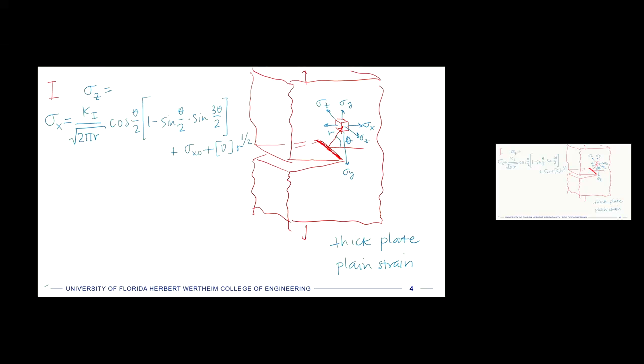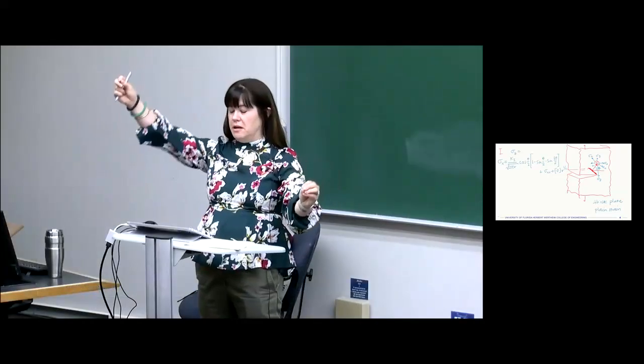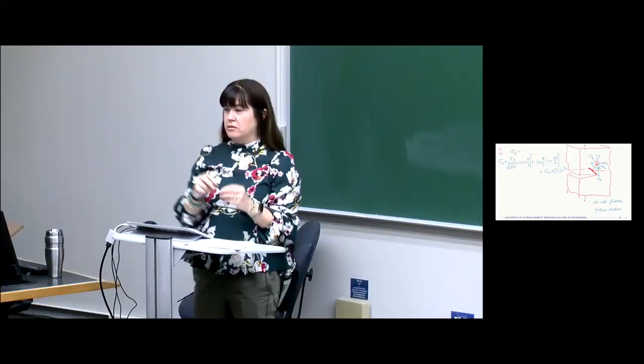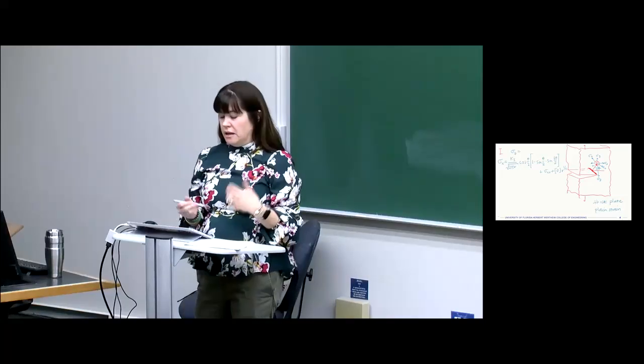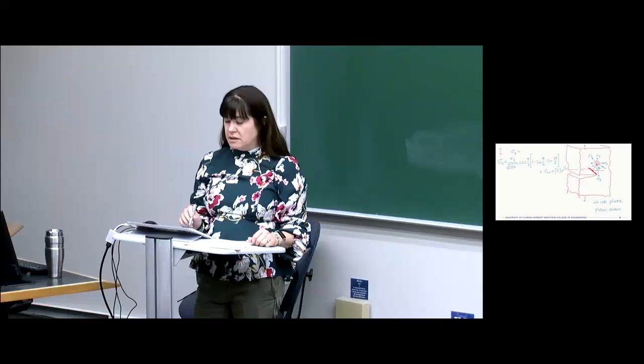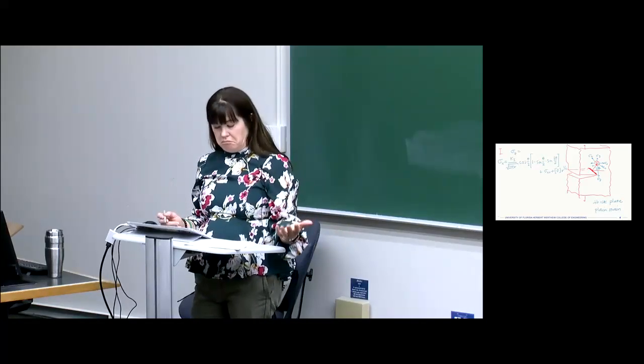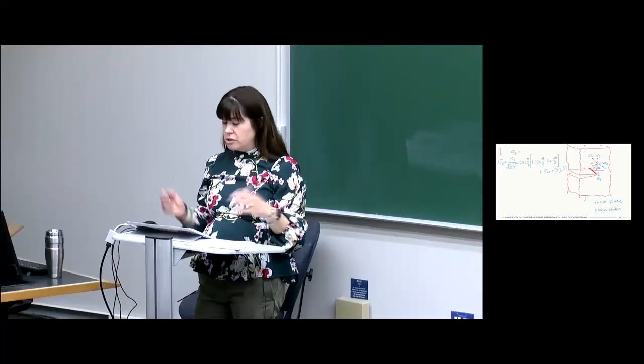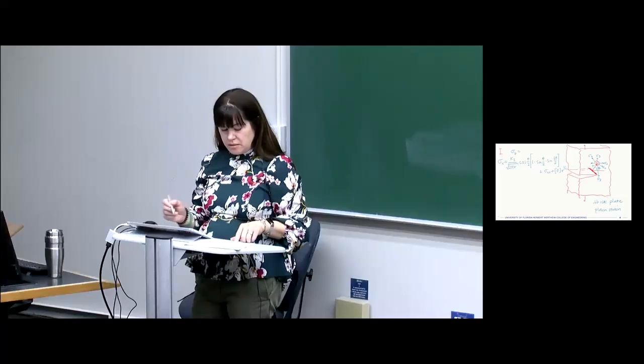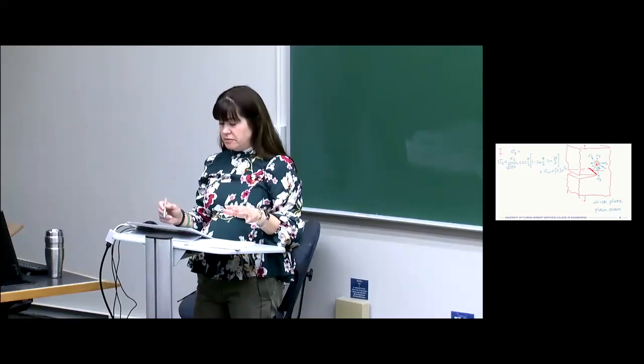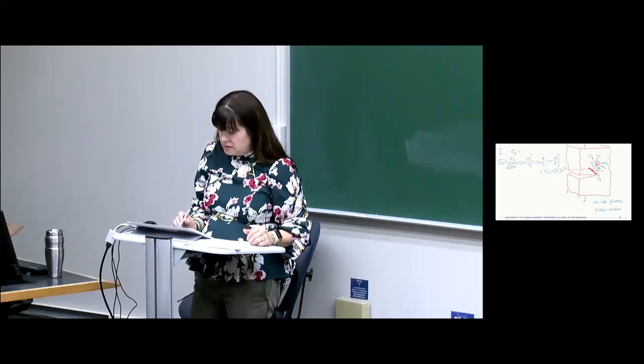So we can look at that equation and see how it aligns with our understanding, right? So we're in mode 1. So we have K1 at the beginning. So that's going to be our fracture toughness in mode 1. And then in the denominator, we have square root of 2 pi r, right? So if you've been in any other classes where you looked at how something at one point affects something at another point in a continuum, we always go with the square root of the distance we are away in polar coordinates. And that's where this 2 pi r comes in. And so you can see here now that when r goes to 0, this stress goes to infinity. So when we're considering this, we don't actually have r go to 0, but we look at what those stresses are locally for non-zero values of r. And then we have a bunch of geometric terms. And then we're adding on this sigma x naught. Let me just underline that so you know what I'm talking about.